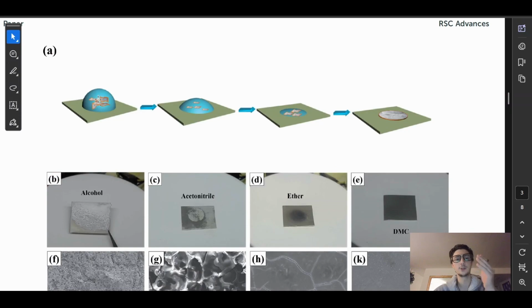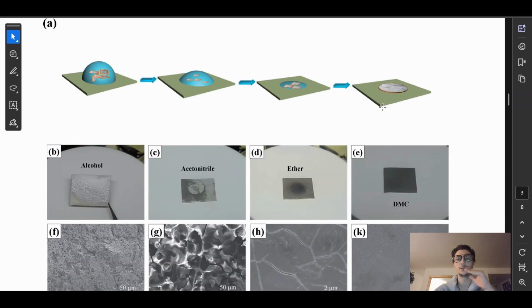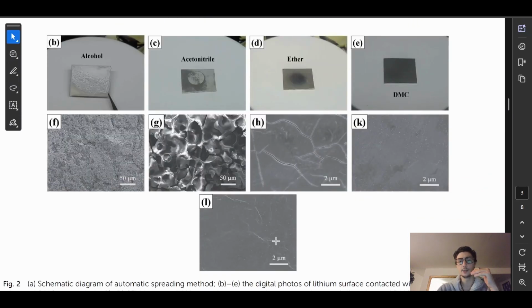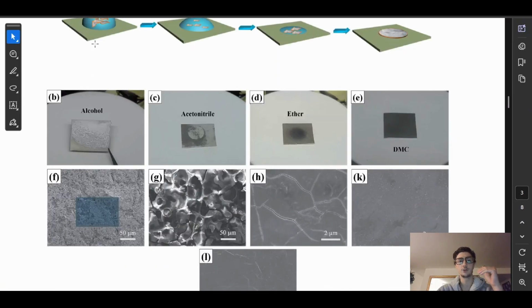They do this kind of deposition technique to get the graphene oxide sheets deposited onto the lithium. This is bare lithium, right? They use alcohol. You can see the graphene oxide sheets look like this. I don't know what this looks like to you, but it looks different than this, right? This is just classic lithium. This is lithium with that little solution with the graphene oxide sheets inside of it just dropped onto it. Looks a bit different, in the digital and the SEM.